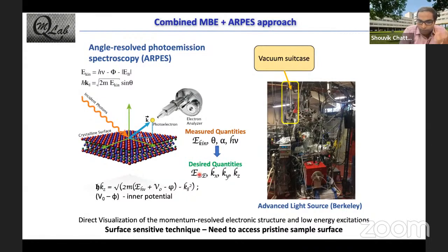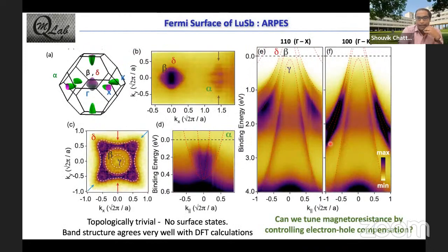you can back calculate the quantum numbers of interest, which are the in-plane momenta and the binding energy of the electron when they were in the solid. And because this is an electron spectroscopy technique, you might readily realize that this is quite surface sensitive. So one needs to preserve the pristine sample surface of your thin film that you have grown. So we developed this vacuum suitcase, which then allows you to transfer the material from one system to another without exposing it to ambient air. And you can see it here attached to an ARPES system. So when we do this right, we can actually get a direct visualization of the electronic structure.